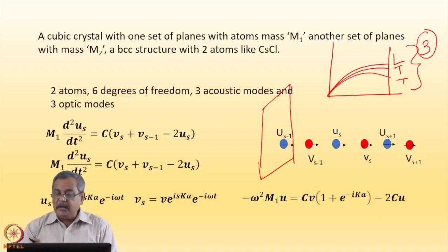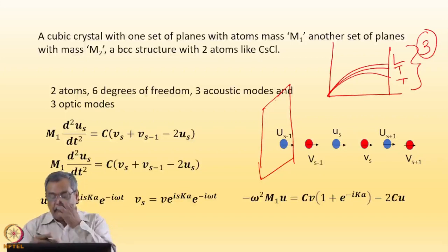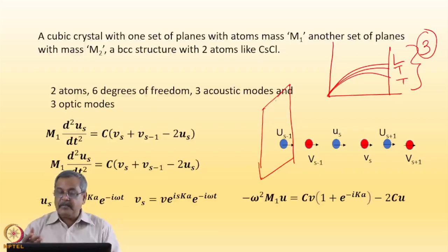phonons. The frequency pattern, or the displacement pattern, is a wave, and when there are a number of atoms in a unit cell, we can find out what is the number of waves that are possible, which you can consider as independent of each other. That means we can break down all the frequencies and all the displacements in terms of eigenvalues and eigenvectors. I'll come to it shortly.